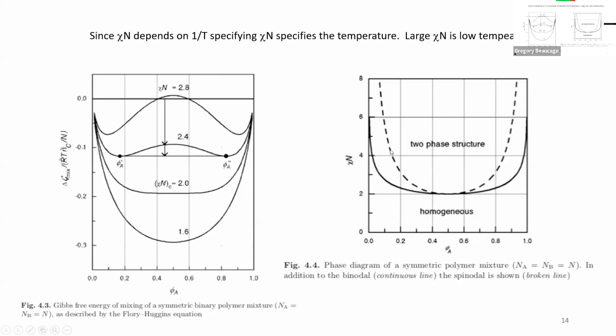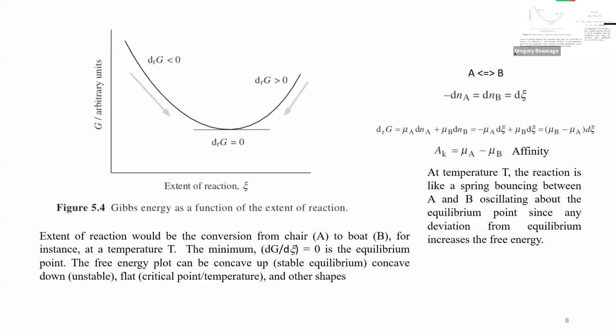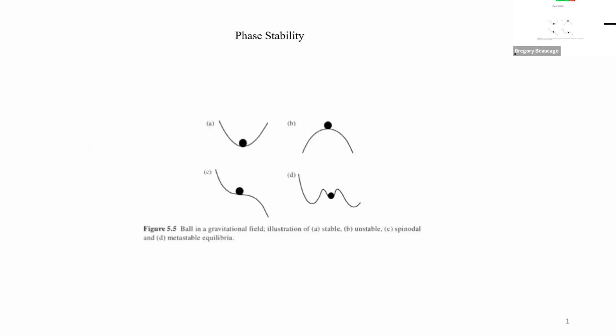So that's going to define this other line within the two-phase region, where if you go to the left, phases need a nuclei to grow. So you get nucleation and growth in that region. Within the middle of it, you get spinodal decomposition, which is that inflection kind of free energy. That's why this shows the inflection point like a spinodal. That's why they're trying to make an analogy. It's not a very good analogy, but anyway, they show that.